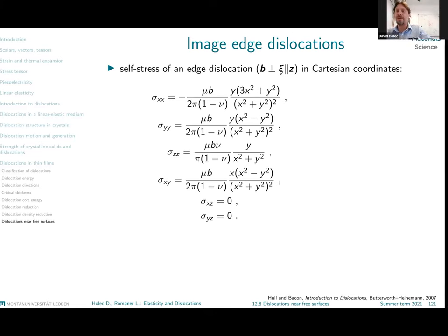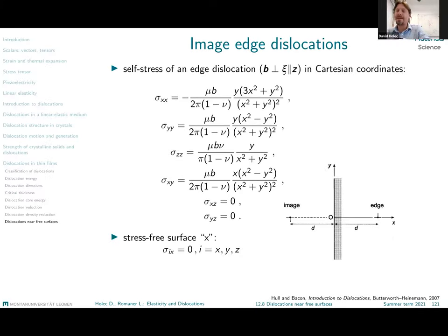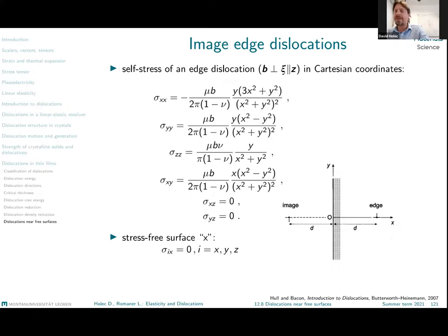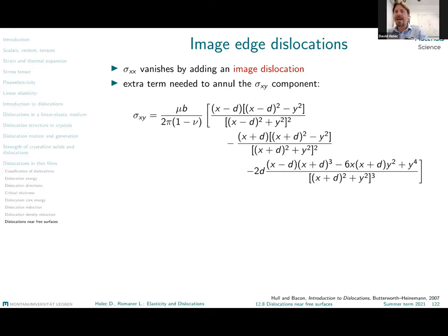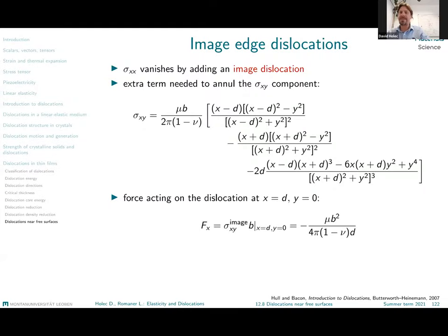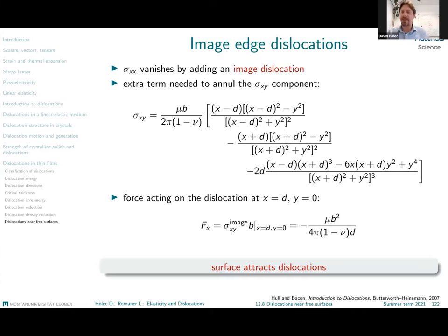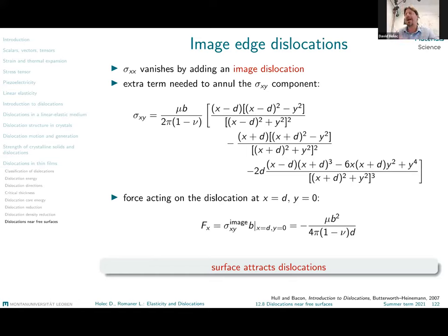Finally, we can have a look at the stress field of this hypothetical image dislocation and how it interacts with the real dislocation. We interpret this interaction as the interaction between the real existing dislocation and the free surface. Using the Peach-Koehler force — the force acting on a dislocation based on an external stress field — where the external stress field is now the stress field from the image dislocation, we end up with the result that the force on the real dislocation is in the direction towards the free surface. So the free surface attracts the dislocation, which can then be annihilated, leaving only a surface step, thereby lowering the energy of the system. The same result holds for edge dislocations: the take-home message is that dislocations are attracted to the free surface.